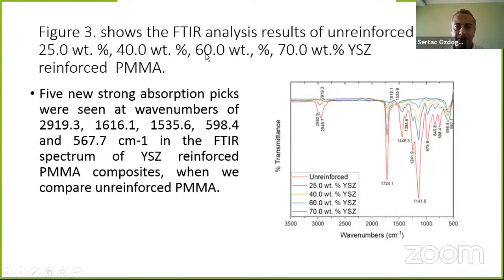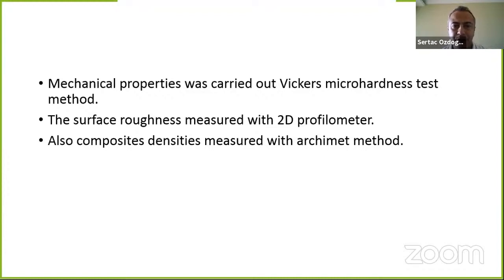Figure 3 shows the analysis results of unreinforced polymethyl methacrylate and 25, 40, 60, 70 addition of reinforced polymethyl methacrylate. Five new strong absorption peaks were seen at wave numbers, as written here, and we compared them with the unreinforced polymethyl methacrylate. We used the Vickers micro-hardness test for comparing mechanical properties, and the surface roughness we measured with a 2D profilometer. Also, composite densities were measured with the Archimedes method.